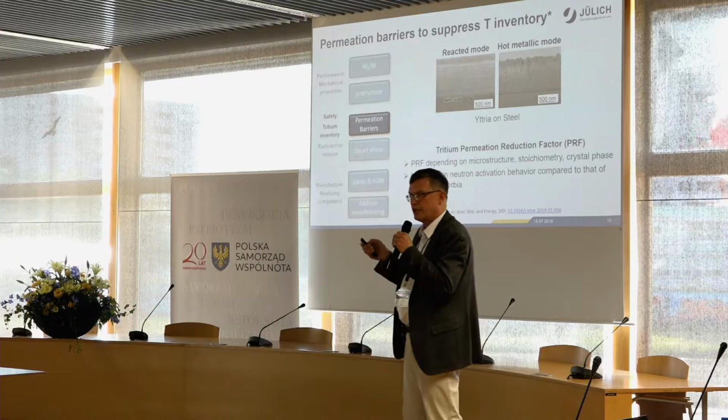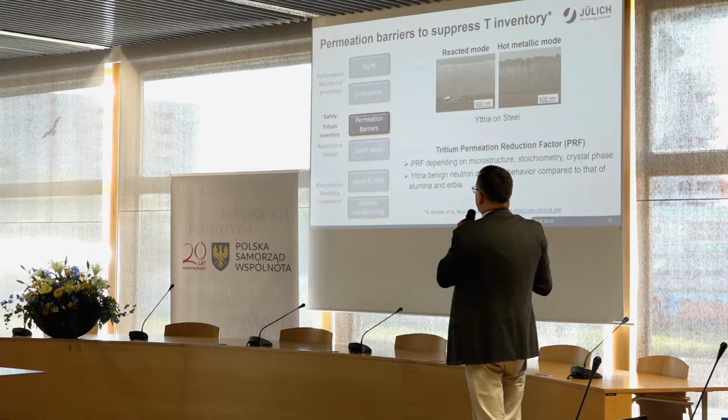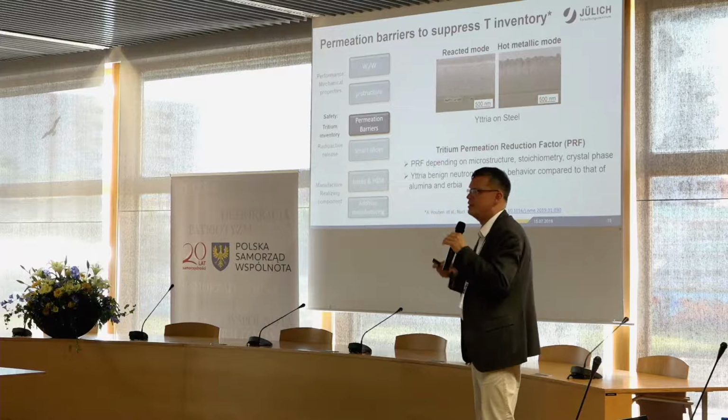And there are several strategies for how we can put such layers. They are all deposited by magnetron deposition, which is also available at industrial scale, in a reacted mode and a hot metallic mode. They differ by oxygen content and the morphology of the samples, and as tested, this is basically the illustration of this performance. If we have a high concentration here and have the tritium barrier, we need to have much lower here. And this is the effectiveness, shown for an input pressure of deuterium up to 1 bar, which is unrealistically high.